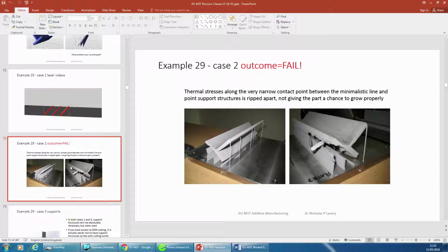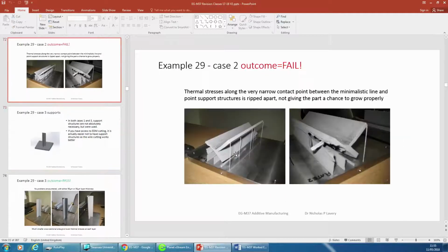Locating at 45 degrees was more catastrophic. It did rip up the part, and you can see the vague logic which was there to try to reduce as much as possible the amount of support structures, but that was quite unsuccessful. The shape came out absolutely distorted, and there was very little that we could do with that.